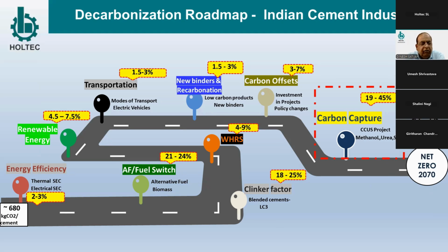WHR 4 to 9%, and then renewable energy will be around 4.5 to 7.5% potential. Transportation, converting to EV vehicles or green hydrogen for transportation, 1.5 to 3%, and new age binders and recarbonation around 1.5 to 3%, and carbon offset by changing investment policies and new project funding also gives a boost of 3 to 7%. And whatever is left out will finally have to be done through carbon capture, which may be around 19 to 45%, whatever is left out of all other efforts.